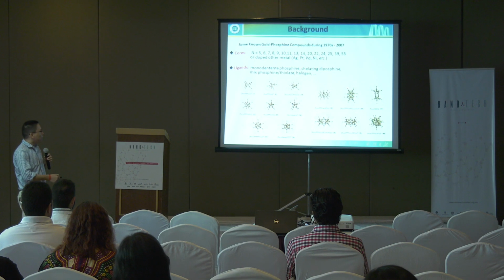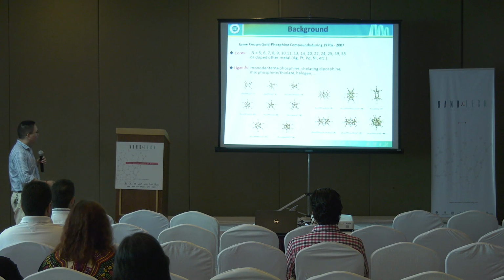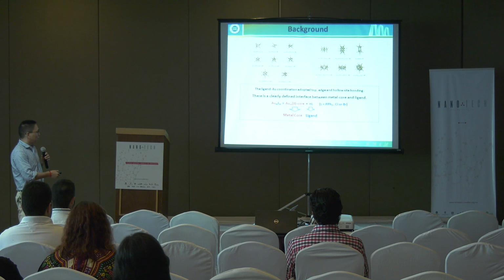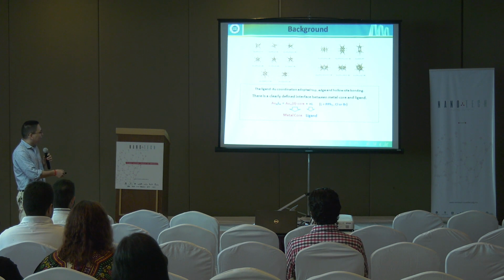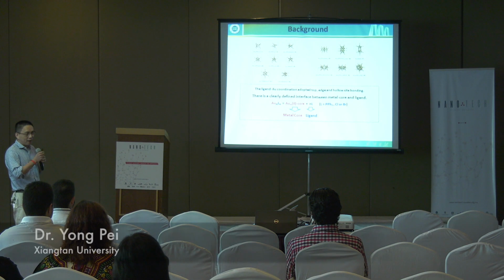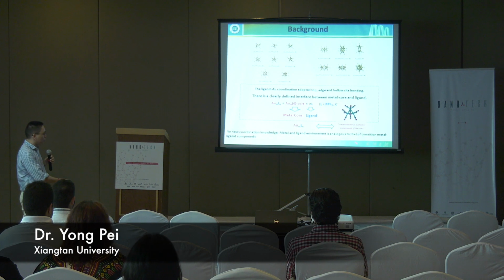Here are examples of gold phosphine clusters synthesized during the past 40 to 50 years. There were many examples. These are crystal structures. From these crystal structures, we found the ligand-gold coordination adopted conventional top, bridge, and hollow-site bonding, so there is no surprise. Why? Because there is a clearly defined interface between the metal core and the ligand, and we can divide the cluster into a metal core and ligands. This is very similar to the already known transition metal clusters with ligands.